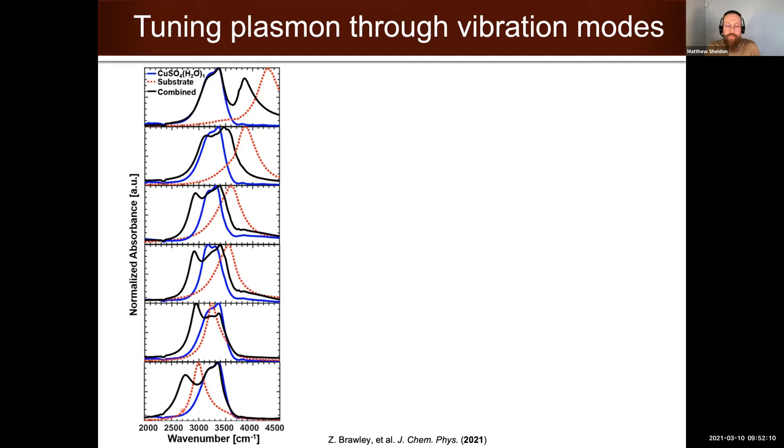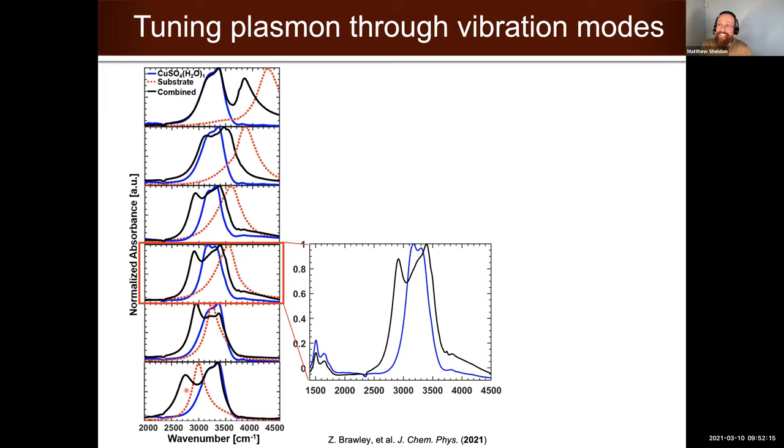Okay, but of course the interesting thing is when we have mode overlap, and we did these experiments, and we immediately thought we could identify strong coupling. Well, I was skeptical that we would see it, I wasn't holding my breath for it, but we saw a signal like this. And we definitely immediately thought, oh, maybe this is what's going on. We have a resonance that's close to the mode, and rather than just preserving the line shape and the spectral features of the two different components additively, we're seeing something fundamentally different. We are not preserving the line shape of the unperturbed salt in blue. Instead, we have broadening, and we also have a decrease of signal intensity in the center, which is where the mode is actually present.